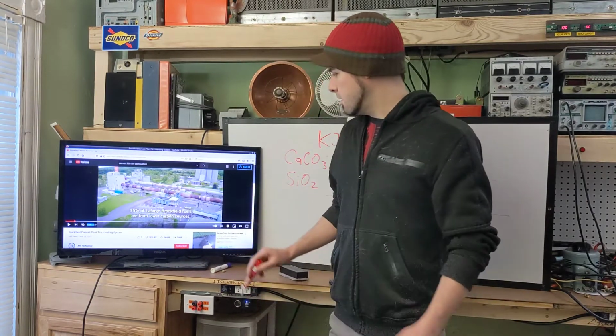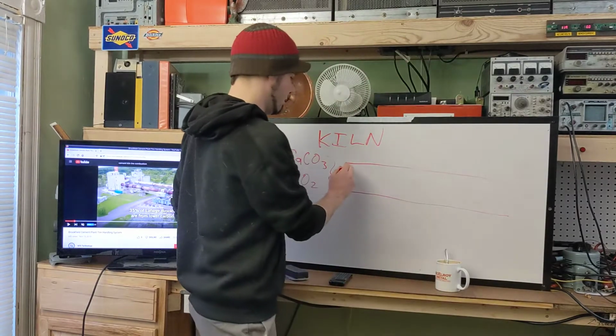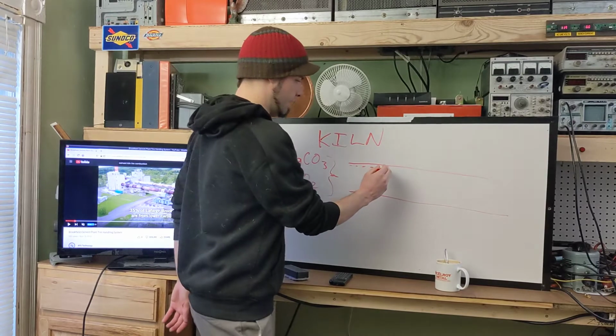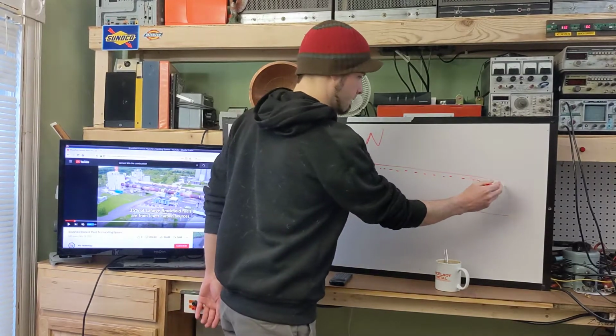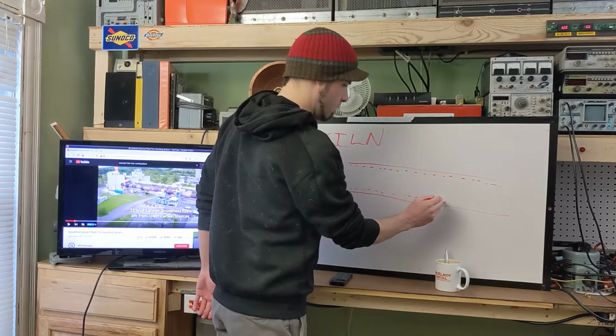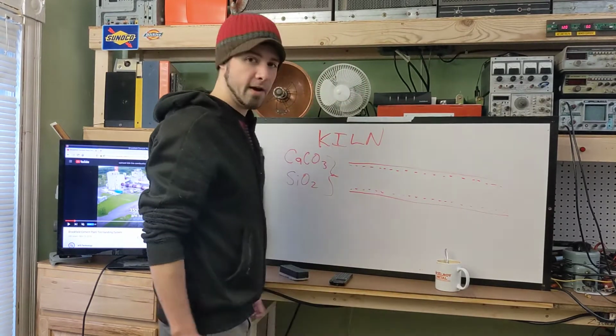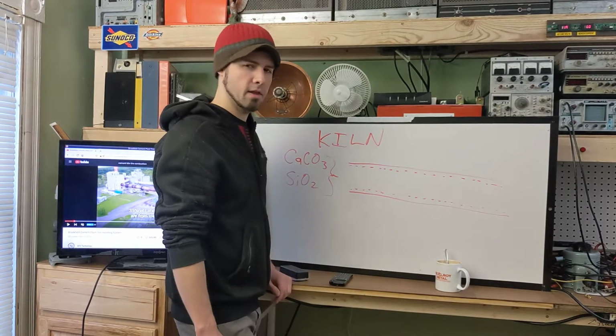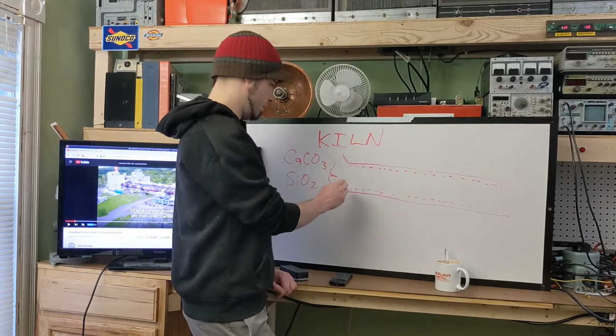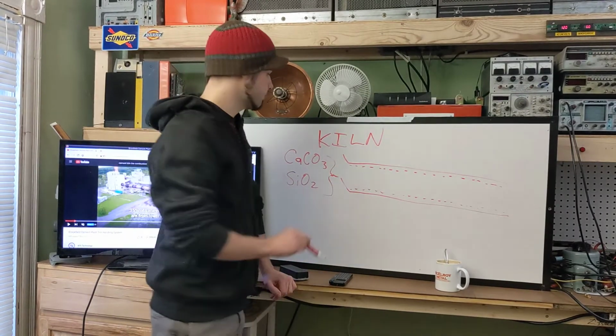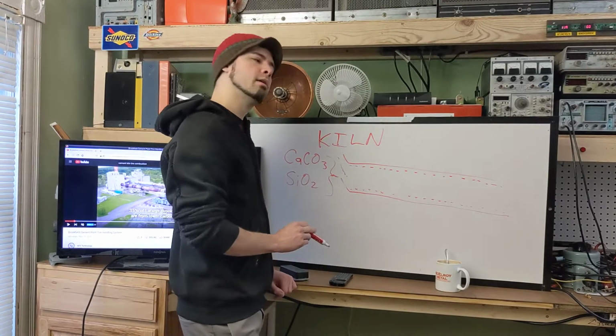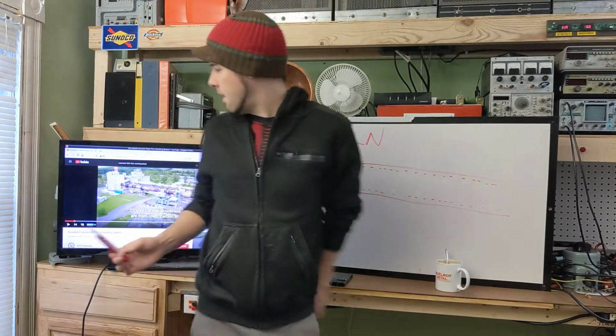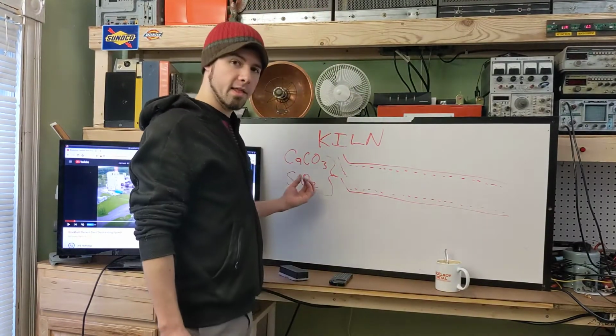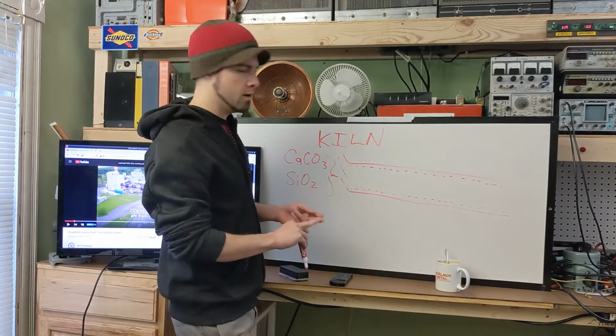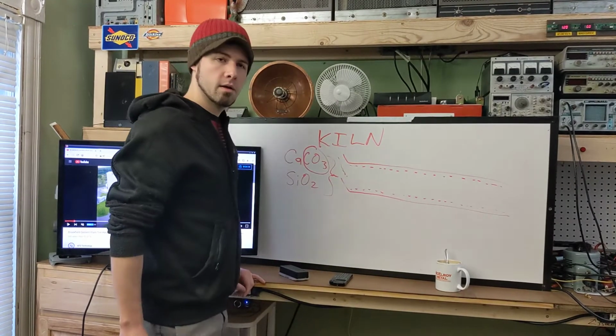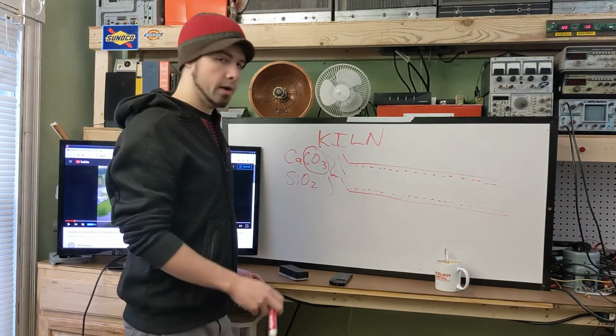So you don't see it in the picture, but inside of there, this whole thing is lined with refractory, heat-resistant insulating material on the inside of that. All right? So it's a steel pipe lined with insulating, fire-resistant bricks or liner. And the cement materials, our calcium and our silicon, are fed into here, preheated. There's an entire structure above this kiln, housed in these buildings, that preheats all this stuff, drives off the water, drives off the carbon dioxide from the calcium carbonate. They call it a precalciner.